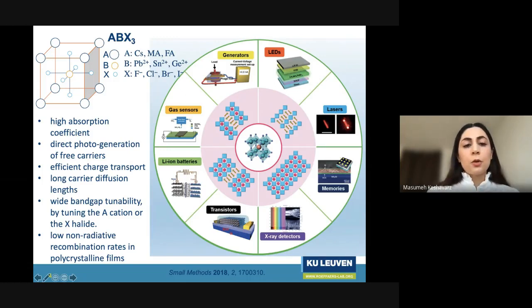Halide perovskites show several spectacular properties, such as high absorption coefficients, direct photogeneration of free carriers, efficient charge transport, long carrier diffusion lengths, wide bandgap tunability by substituting either the cation A or the halide X, and they also show low non-radiative recombination rates in polycrystalline films.